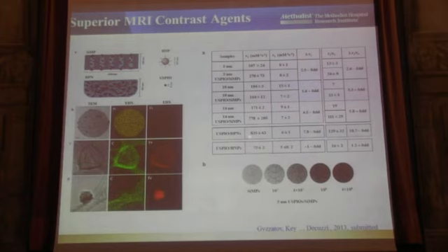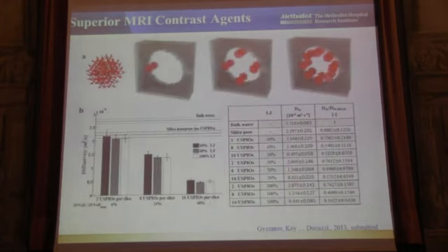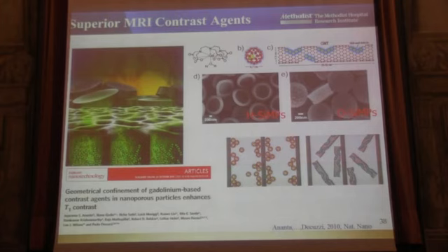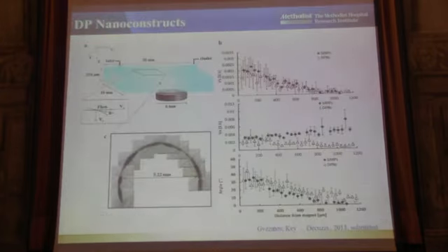But what is more interesting is that in terms of relaxivity, the MRI properties, you start with USPIOs that are 100 millimolar sec-1 in relaxivity, which is a way to measure the contrast enhancement that can be generated from that particle. The same nanoparticles, 5 nanometers, loaded into these hydrogel-based nanoparticles, give a signal which is at least 8 times larger. So there is a massive enhancement, a huge concentration of iron, massive enhancement in MRI properties, with additional characterization and modeling of why this is happening. We have also shown in the past that this enhancement in relaxivity happens for gadolinium.